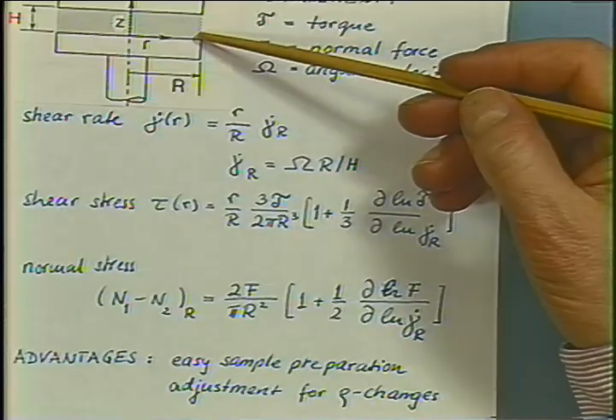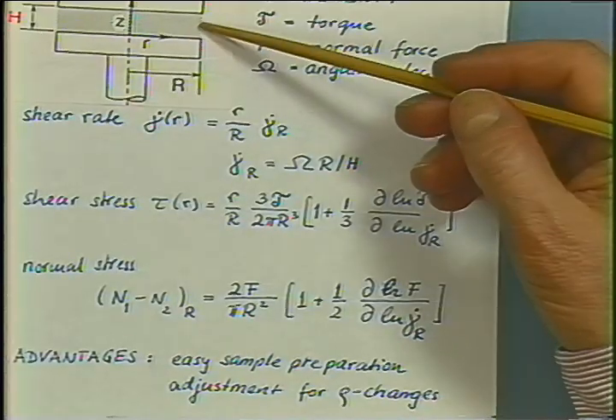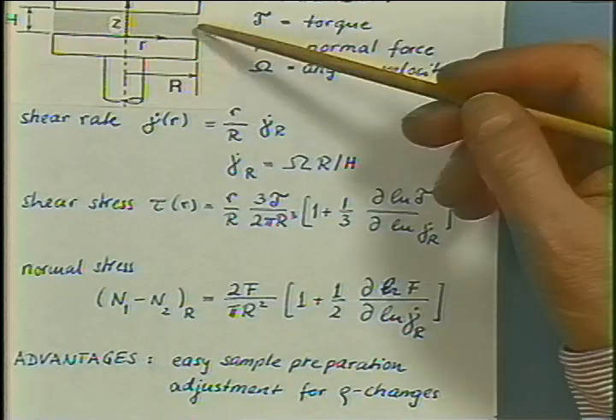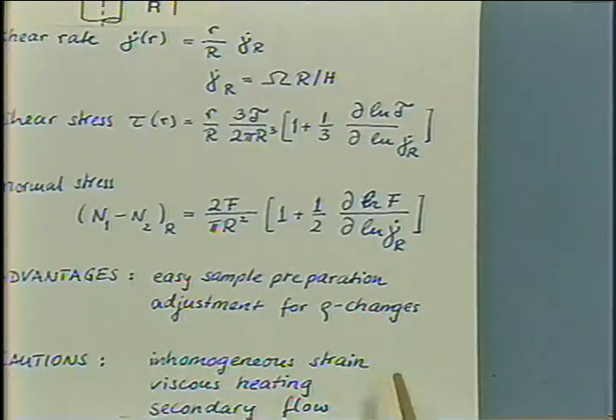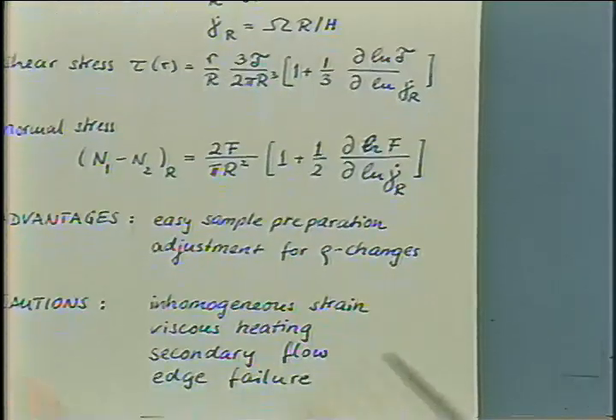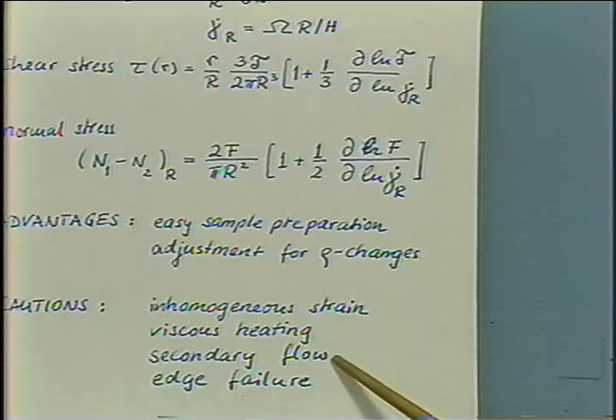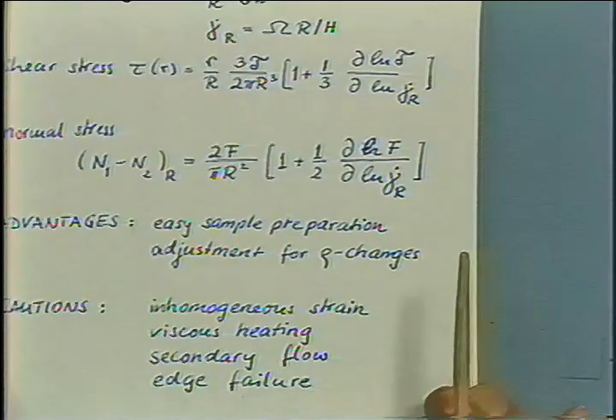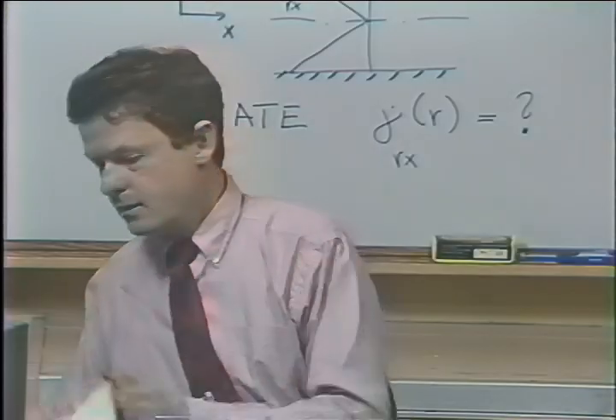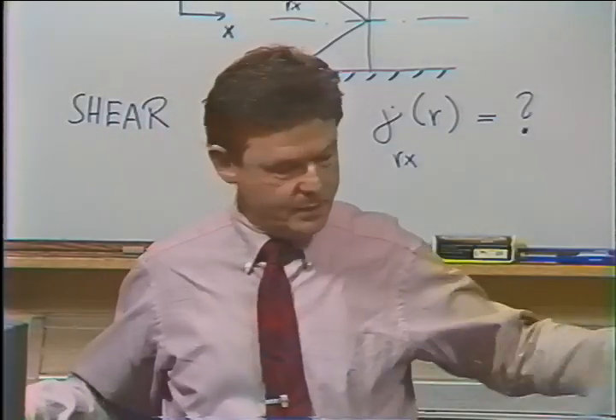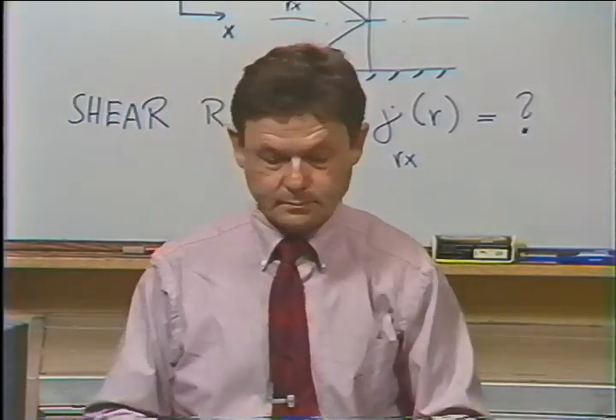It's the nicest treatment for your sample, let's put it this way, for your experiment. But the strain is inhomogeneous, and the other problems are the same as in cone and plate geometry. You might have viscous heating or this secondary flow or edge failure at high rates. So there you might not gain anything. In general, it's about the same.